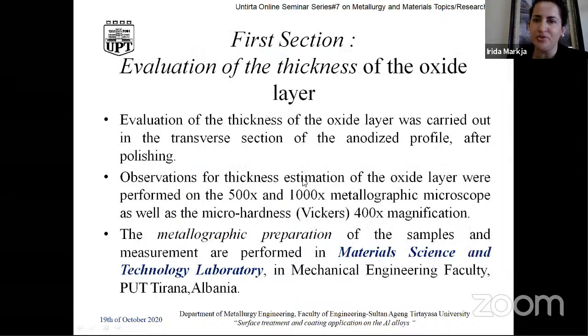The first section of our study is to evaluate the thickness of the oxide layer created after anodizing. First, we prepared the transverse section of the samples of the anodized profile, after polishing and metallographic preparation in our laboratory. Observation for thickness estimation of the oxide layers was performed with 500 and 1000 magnification with an optical metallographic microscope, and micro hardness Vickers with 400 magnification. Metallographic preparation and the equipment we actually have in our laboratory, and it was performed in the material science and technology laboratory in our faculty.